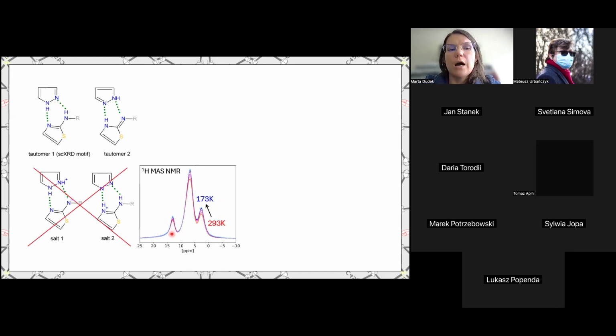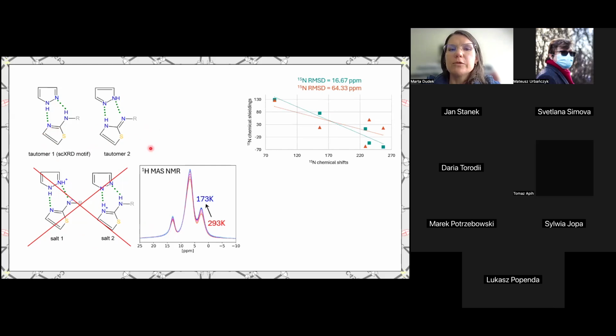We also didn't find those two salt structures stable in our DFT calculations, so they converge to either the first or the second of the tautomers. So we excluded them further. But when we calculated those two tautomers and calculated nitrogen chemical shifts, you can see that the RMSD values for neither of them are in agreement with experiment. They are really, really off.